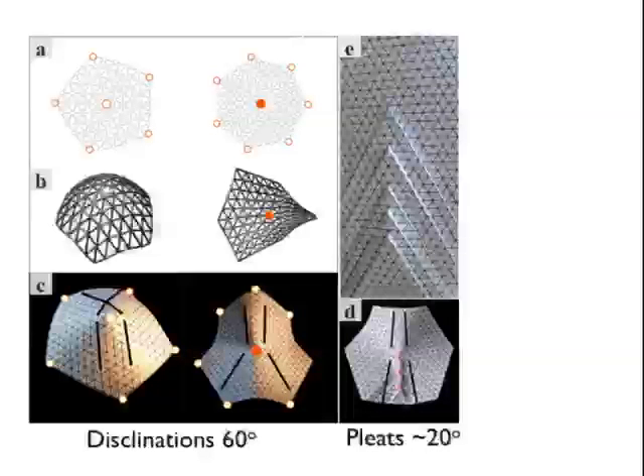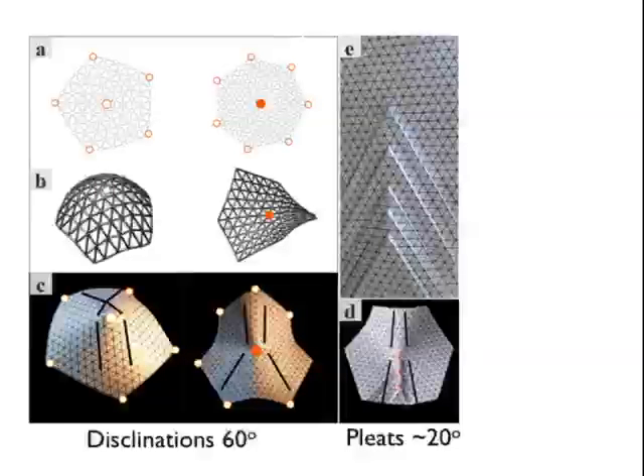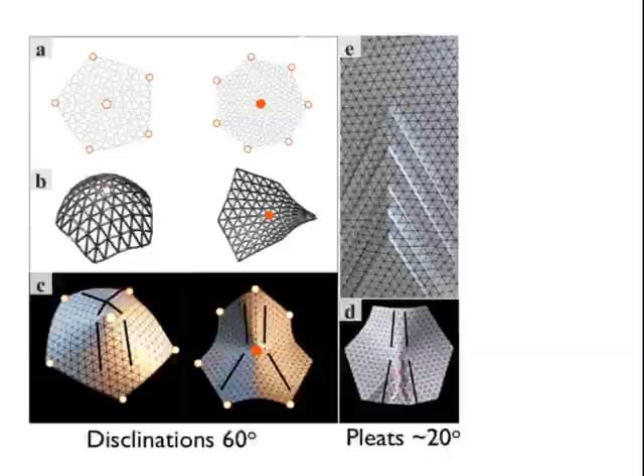And if you like, the analogy is the following. If you have dipoles, they give you a polarization. If you have a uniform polarization, you have a uniform polarization. If you have a gradient in polarization, you get polarization charge, right? That's, for example, what happens in a capacitor. You have polarization, the capacitor material ends, and you have surface charge, and you have surface charge on the other side. So if you have gradients, you can get charge, which is like topological charge, which is like disclinations, which is something that will give you Gaussian curvature.